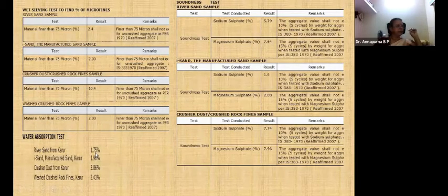Now, water absorption. In the river sand water absorption test, it is observed that it is 1.75% water absorption. Manufactured sand is 1.96%, crushed rock dust is 3.86%, and washed crushed rock is 3.43%. These materials are obtained from Karur. All these materials, river sand, manufactured sand, crushed dust, everything, are taken from the Karur area. So this is the water absorption test.